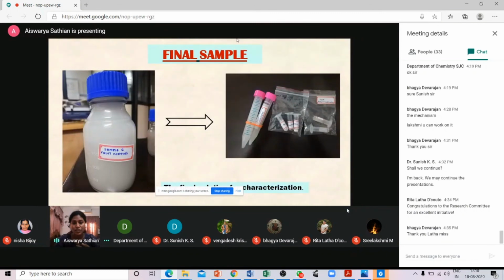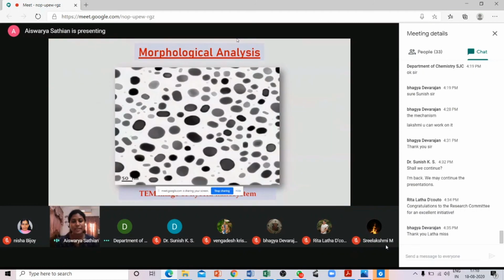I took the morphological analysis, TEM image. Here you can see the quasi-spherical structures which have a size of 50 nanometers. You can see the darkened portion which shows the right encapsulation. There is no breakage in the outer wall also. That's why it has a quasi-spherical structure. If it has a breakage in the outer surface, the encapsulation does not happen. So in this TEM image, we can see it has the right encapsulation also.